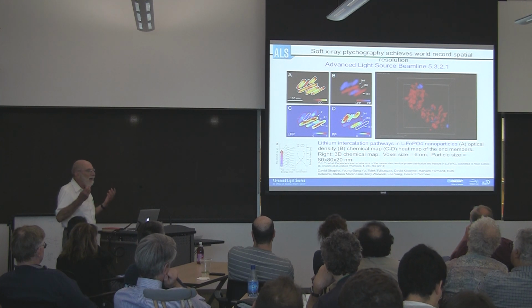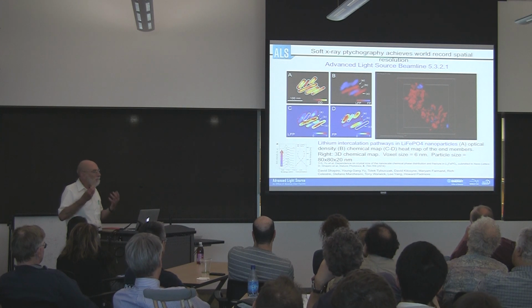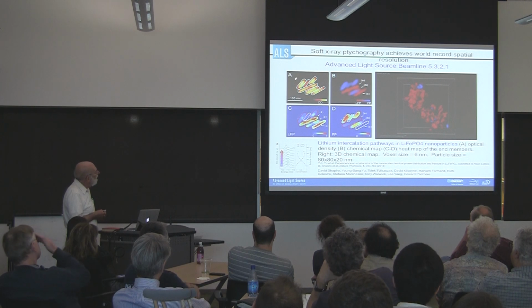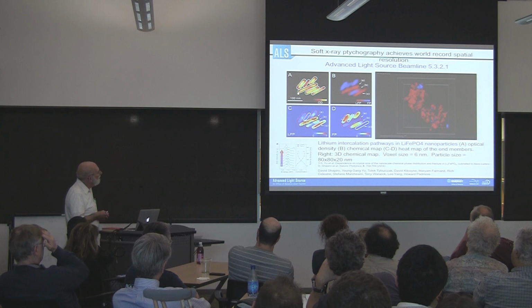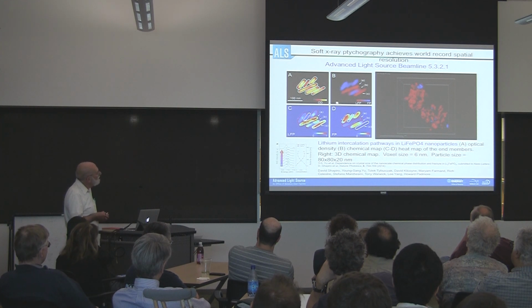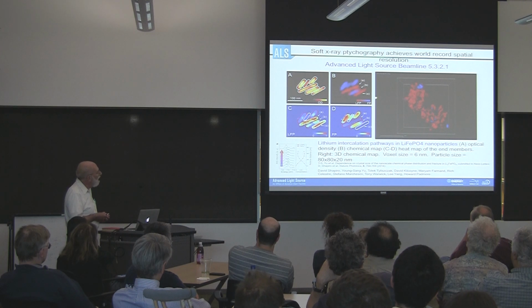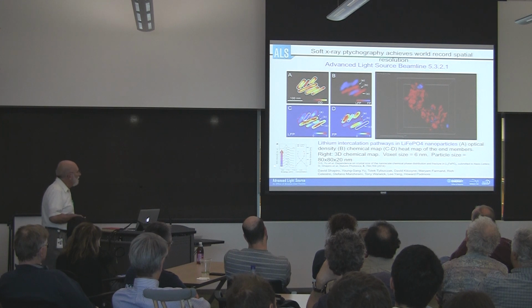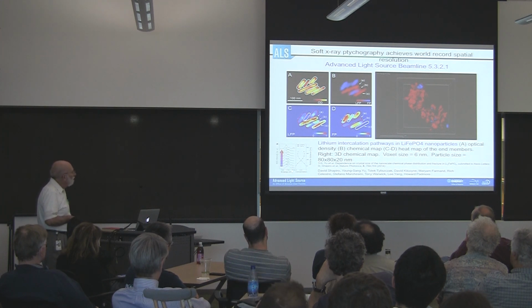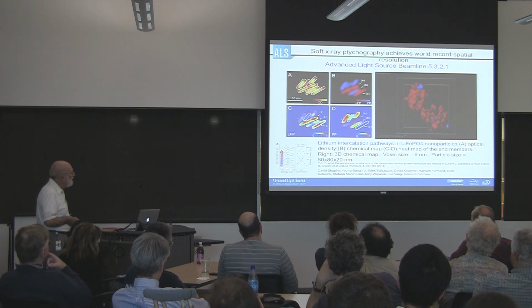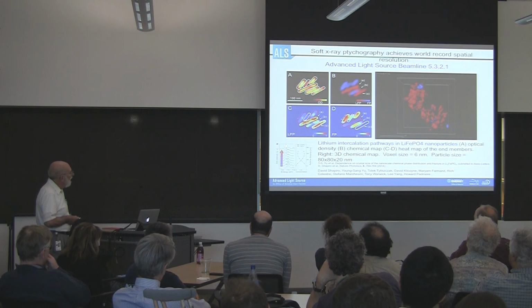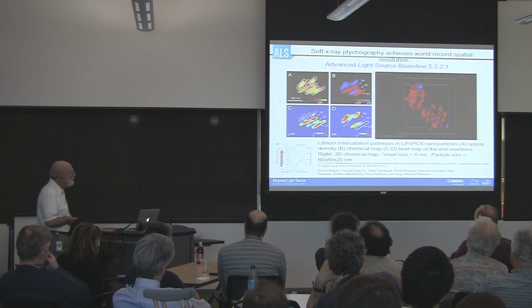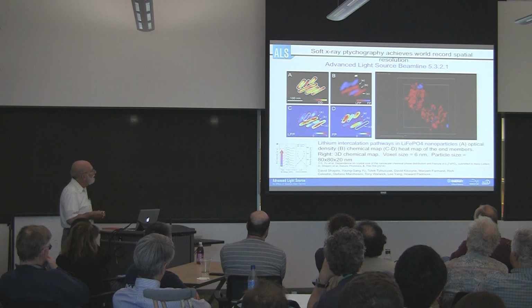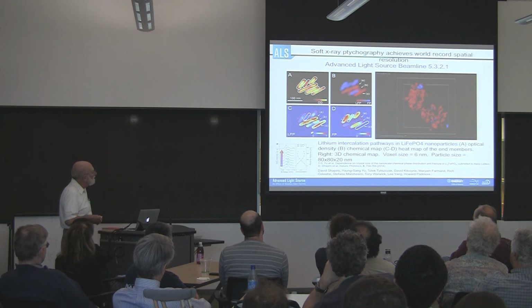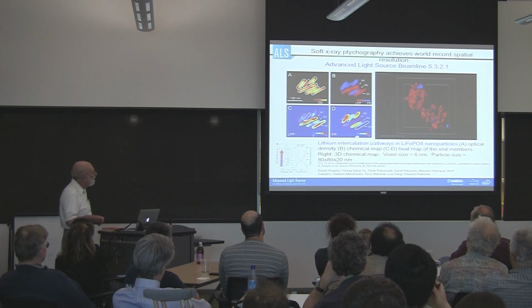In these lithium batteries, the migration of the lithium ion is the critical component. And you can see if you look at these nanorods that are here, that this is just an optical density image, but here you see it with the chemical information where red is lithiated iron phosphate and blue is unlithiated iron phosphate. And you tell them apart because near the iron L absorption edge, the pure iron phosphate, which is this lowest curve that you can't see, has a peak at above 710 eV, while the lithiated iron phosphate has a peak which is closer to 708 eV. And so you can tell apart what is lithiated and what is not. And so this is a map of the lithiated iron phosphate, and this is a map of the iron phosphate.